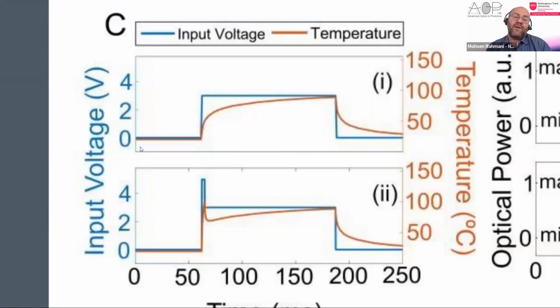A very important thing here is how we apply this voltage. If you apply from 0 to 4 volts, the metasurfaces get heated, and it takes up to 17-18 milliseconds here. I will show you later. So it is really fast, milliseconds, but it still is longer than what we can see by our eyes, because our eye can see around 10 to 13 milliseconds. So we need a shorter switching time, so that we could use it for real applications like displays. And here is the strategy we took.